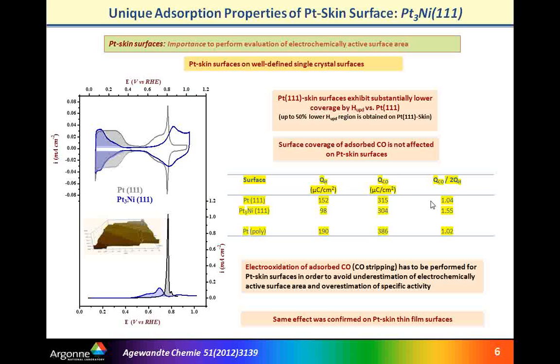And the key for all of this is that, in the case of platinum 111, if one would compare the charge required for formation of hydrogen UPD layer and stripping of CO, the ratio is usually 1. However, in the case of platinum-3 nickel nanosegregated structure, the ratio between the charge for CO and hydrogen is 1.5. So the only way to know the number of active sites, or even to demonstrate that the platinum-3 nickel structures have nanosegregated domains, is by following the ratio between the charge required for formation of hydrogen and CO adlayers.